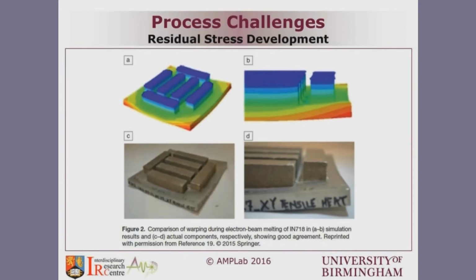This is the results from one paper by Professor Das, looking into the distortion due to electron beam selective melting in Inconel 718 nickel superalloy. 718 as an alloy is known to be weldable. Actually, it's an alloy that you can build with additive manufacturing without seeing a significant amount of cracking.